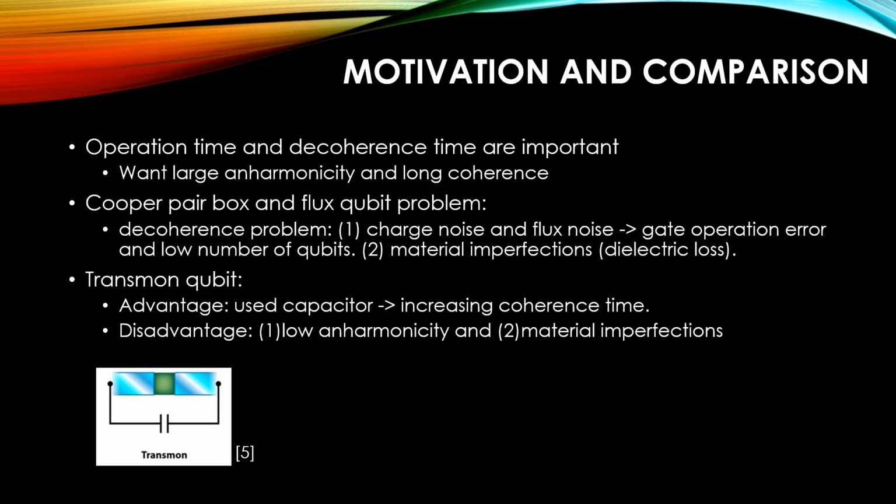Dielectric loss means there are microscopic two-level charge defects residing in the interface oxide layer of a typical thin-film device. As a consequence, each circuit capacitance acquires a non-zero dielectric loss tangent, which induces the energy relaxation of the qubit. Then scientists had the Transmon qubit.